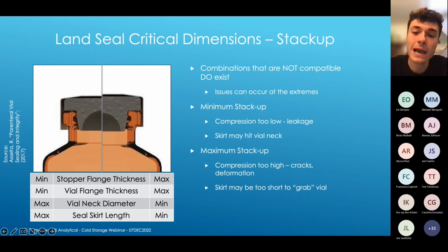When we think about this minimum stack up, given a constant set of crimping parameters, we might yield low compression in this case as a result of these minimums. We might also see that when we go and apply that crimp and tuck this skirt under, because this skirt is so long and this vial and stopper flange are so short, there's a lot of excess material hanging out. And so when we go and actually apply this crimp seal, do we get contact with the neck of the vial, which can, one, introduce things like scoring or cracks, or two, prevent that crimp seal from being properly applied and adequately compressing that stopper against the glass.